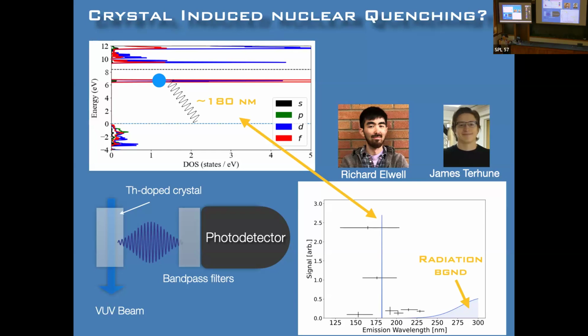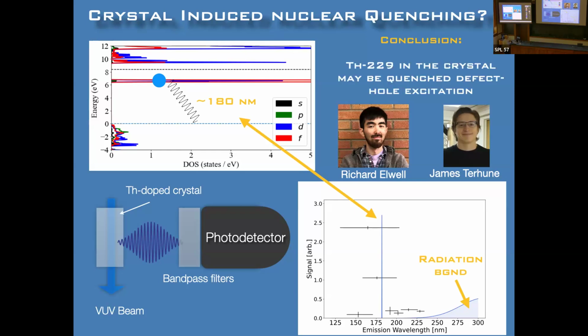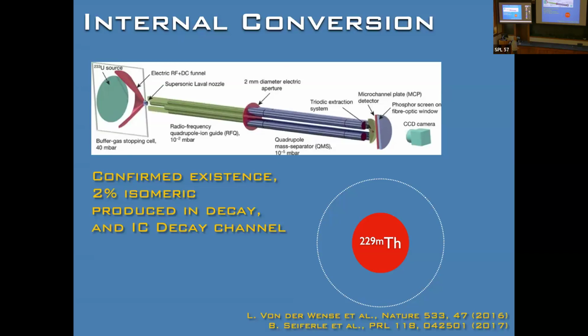It was actually scarily right on top of what they had predicted. So we had concluded that the thorium-229 in the crystal was probably quenched by this defect hole excitation. And our dream that we had had for over a decade of driving this transition in the nucleus was probably dead, or at least much more complicated than we thought. So we turned our attention elsewhere.